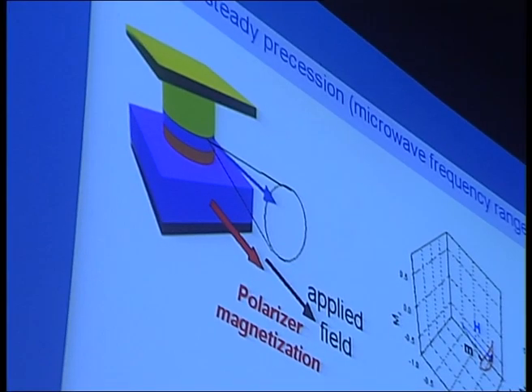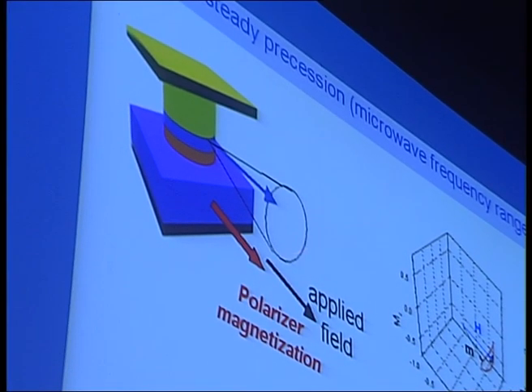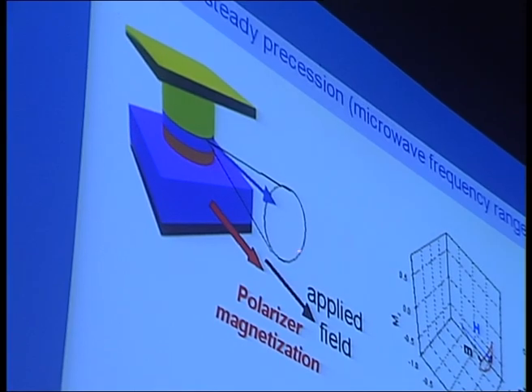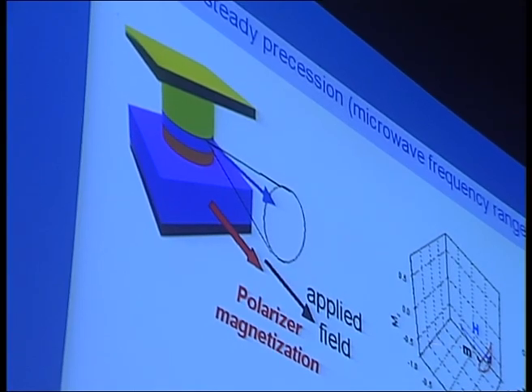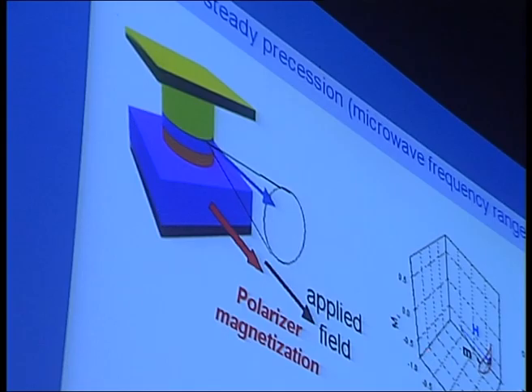The second regime of spin transfer is when a field is applied. When you apply a field on the system, it becomes harder to completely reverse the magnetization, and so the only solution for the magnetization is to precess. You can see an example of the trajectory of this precession.